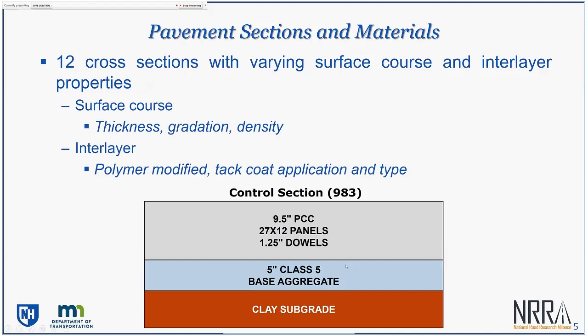And they are changing in terms of thicknesses. Also in terms of mixes, and when I say mix, that's not just mix as in different air void levels, but also mixes in terms of, to some extent, different gradations. Several of these sections also have interlayer treatments, or another asphalt layer that might be between your traditional overlay mix and your concrete slab. And construction technique as well, where several of these were constructed using a spray paver, doing a thin bonded overlay type of construction technique, where you can get a higher tack coat application, and through the study then evaluate what advantage you may have in terms of reflective cracking or not.